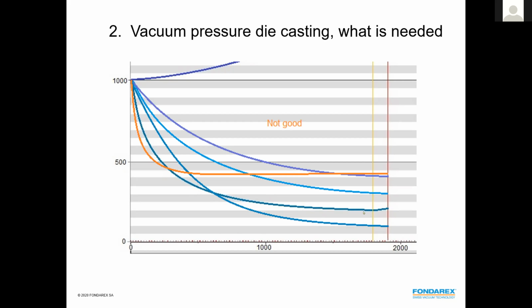Now, how good this vacuum curve is sometimes shows directly in the result, or rather we have to talk about which curve does not influence the metal flow as much and does not get additional air into the die. So that curve, if we talk about pressures, about how much pressure we have to create, there are many, many differences in the world of die casting. And it's not that one pressure, like 200 millibar, is good for that part. We have to gain experience on one application. We have to make 100 shots, 200 shots. We have to X-ray the parts. We have to adapt the parameters. And maybe after 200 shots, we know 150 millibar with those parameters is good for this application.